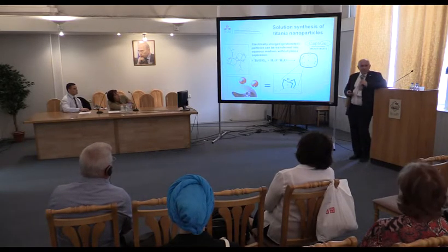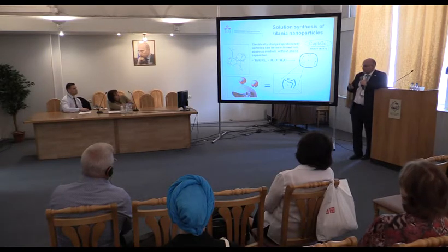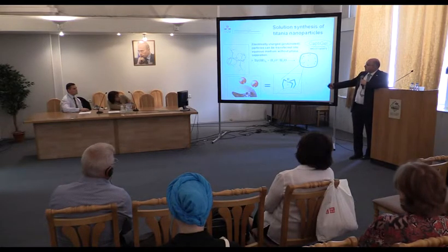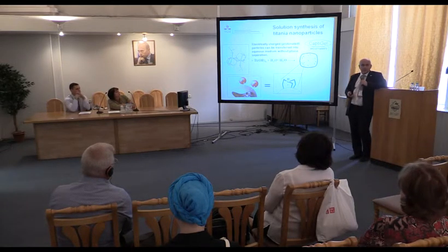Why is this interesting? Well, it means that it is possible to stabilize particles in solution using very simple biocompatible organic ligands. What we have patented was the application of triethanolamine. It is possible to use a complex bearing this kind of ligand, to charge it by addition of acid in hydrolysis, and then particles which are stabilized by positive charge are produced, and then very stable.